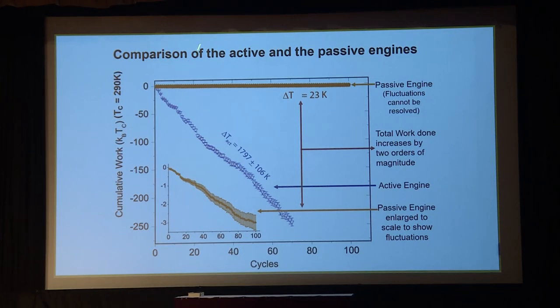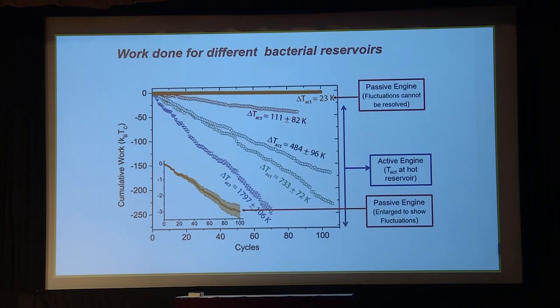And we showed that without the bacteria, this was the cumulative work done, very, very small on this scale, expanded here, 10^-3 in this unit. But when we put in the bacteria between this low and high activity, you can see that it increases 250 times. So we can now use the bacterial activity to make it a non-equilibrium reservoir. And we showed that indeed you can do it with various activities of bacteria.